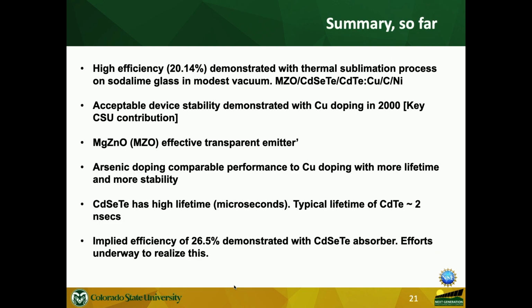So here is where I want to summarize our work with cadmium telluride. We have high efficiency, 20.14%, demonstrated with thermal sublimation on soda lime glass. And this is all done in modest vacuum. You don't have to pull the vacuum to 10 to the minus 8 or minus 10 or something like that; even just 10 to the minus 3 and minus 4 vacuum level is good enough to make good devices. And the structure that we have evolved is MZO, cadmium selenium telluride, cadmium telluride, copper, carbon, and nickel.